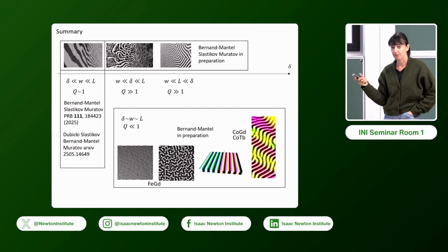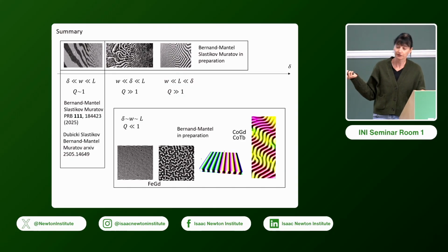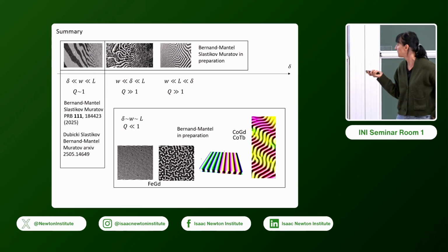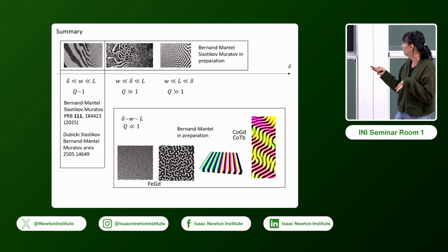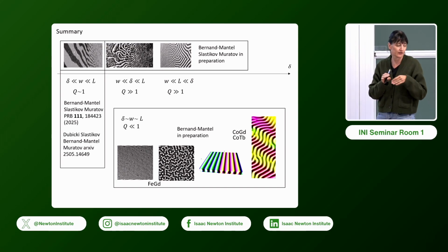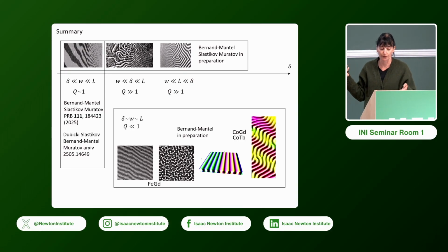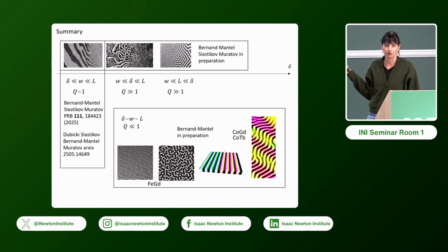And in fact, here what you obtain is something close to an artificial spin ice system, but where we didn't have to do any patterning. I mean, nature is creating this dense, hexagonal compact array of skyrmions with these two types, and now we can study the physics of interaction between these two types of skyrmion. And we also observe some interesting phenomena related to the presence of two types of walls. So we observe some in-plane domains of magnetization, and this is because we are close to the in-plane to out-of-plane transition. So this work, I'm going to present in more detail in our workshop happening in Pisa in October for those who will be there.